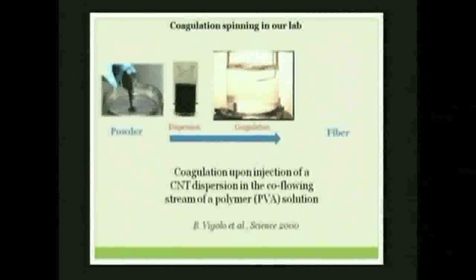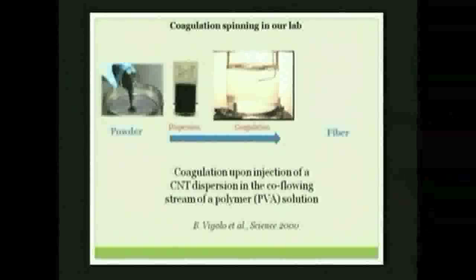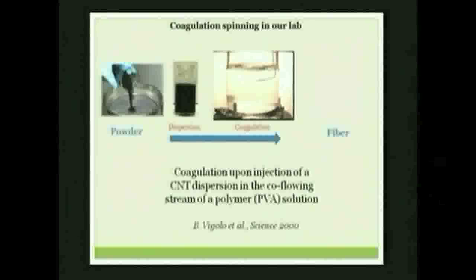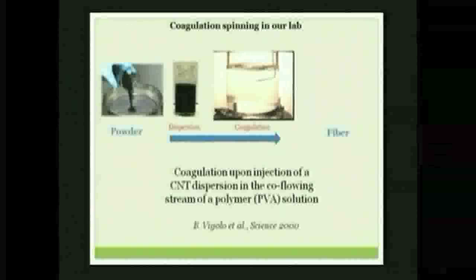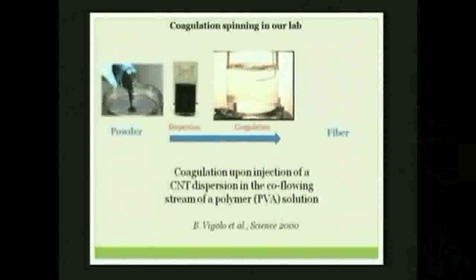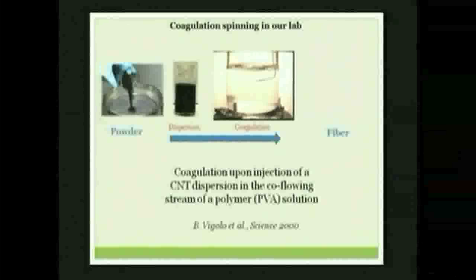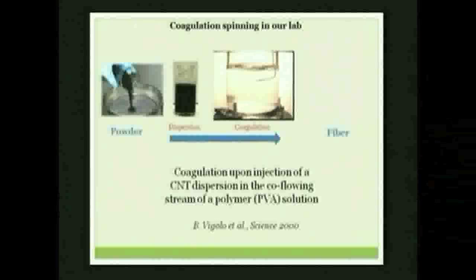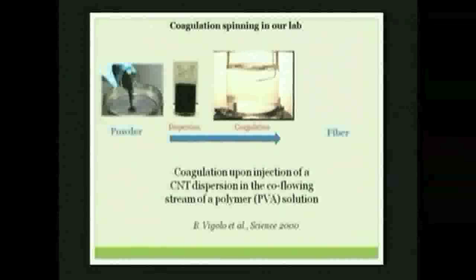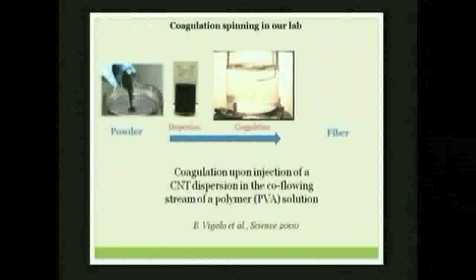Let's come to the coagulation spinning that we proposed in our lab. What do we do? We take the carbon nanotube powder. The first step is the dispersion of this carbon nanotube powder into water. Because nanotubes are insoluble in almost any solvent, you have to use surfactants. So we use surfactants. These surfactants are adsorbed on the surface of the nanotubes, and they induce the dispersion of nanotubes into water.